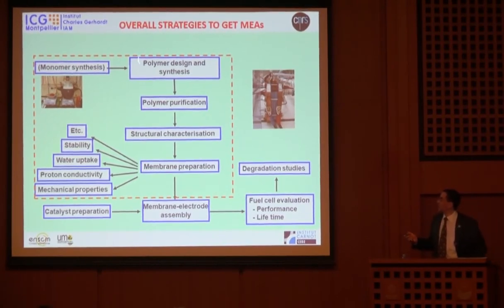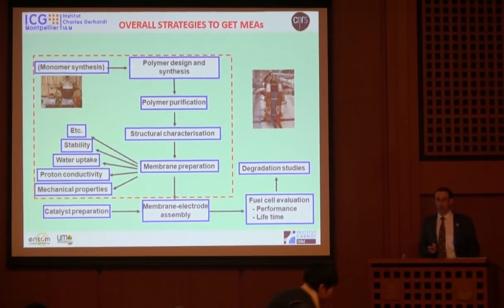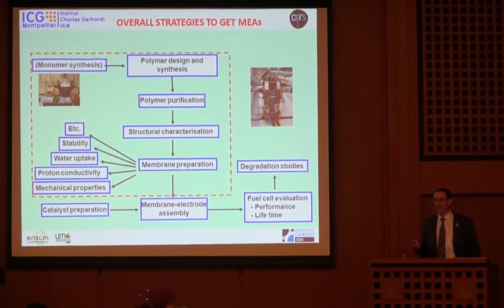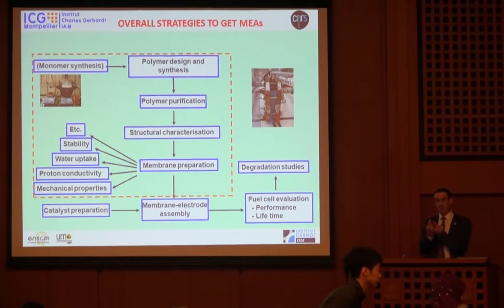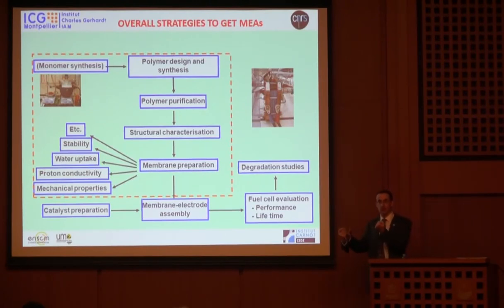Then this monomer being achieved, you have to make the polymer, by homopolymerization or copolymerization. Of course, I won't go into details about kinetics. It depends on what you use. But when you have two monomers, if you start from 80-20 in the copolymer, you don't necessarily get 80-20. So you need tools in order to investigate the concentration and the composition of the different monomers in your polymers. So this means that you really need polymer people. And I know in Kyushu you have a lot of good ones here. Polymer purification, structural characterization, which is very important. I will not talk about that, but the design of the polymer is very important, and how the system works with hydrophilic clusters in a hydrophobic matrix, how this is important.